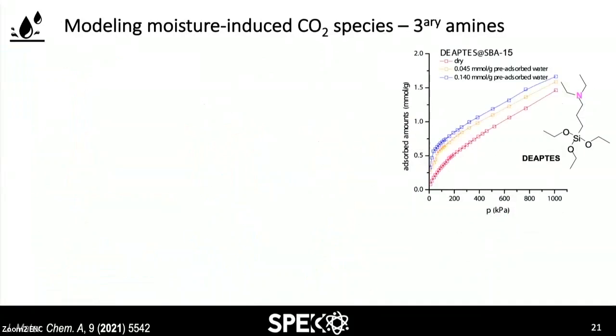Now going to tertiary amines, here we can see that there is a change in the adsorbed amounts of CO2, either if you are in dry or in wet conditions. And we have here the dry in purple, we have a tiny amount of water and a little bit more water in blue. So as you increase the water content, you also increase the amount of CO2 adsorbed.